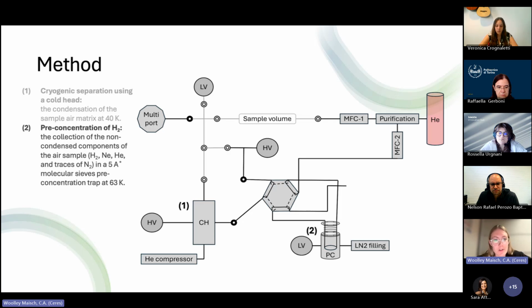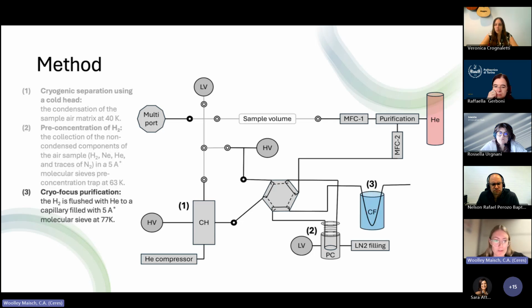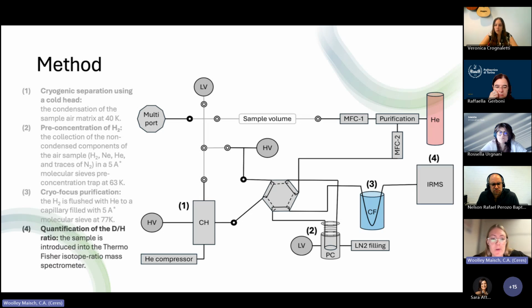So then we have pre-concentration. At the cold head, it's at 40 K, so almost everything condenses except the hydrogen, the neon, and the helium, and some N2. And then we have a molecular sieve trap, which traps everything else, and then another cryofocus trap. And then basically we are left just with hydrogen, and then we inject that hydrogen into a Thermo Fisher IRMS to get the ratio of the DH.